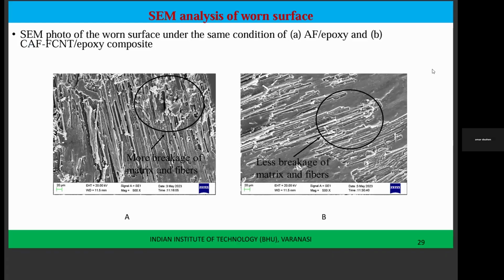Next slide, please. After this tribological test, when you take that sample, clean the surface, and keep it under the microscope, you can see how the matrix and fiber appear. There is more breakage of the matrix as well as the fibers in the case of the uncoated one. When you apply the load, if it does not have sufficient strength, it will fail with less load itself. That means there is no proper bonding between the matrix and fibers. For the second case, you have to apply more load because it is strong enough. It has proper bonding because of oxidization, and you can see less breakage of the matrix and fibers. Next slide, please.